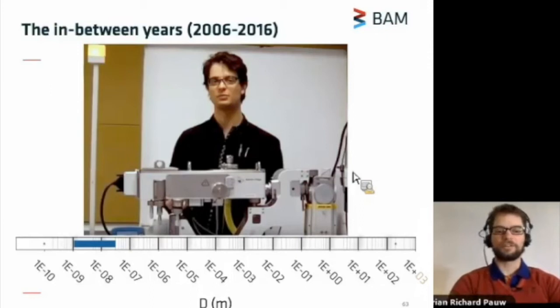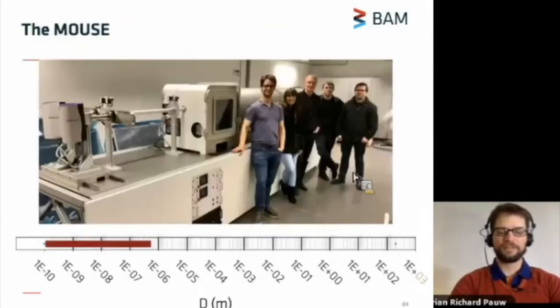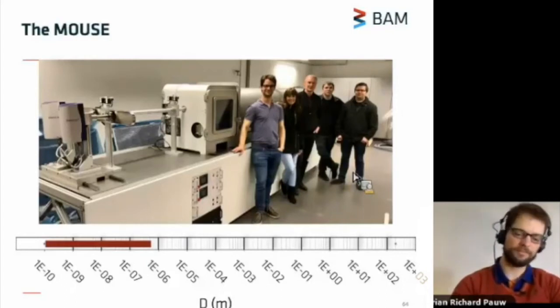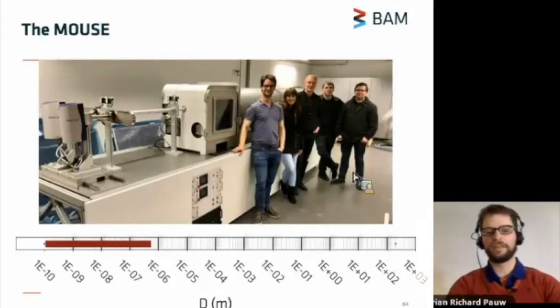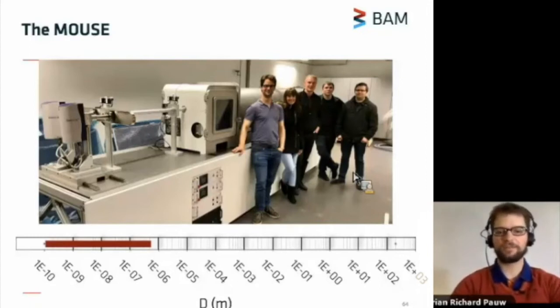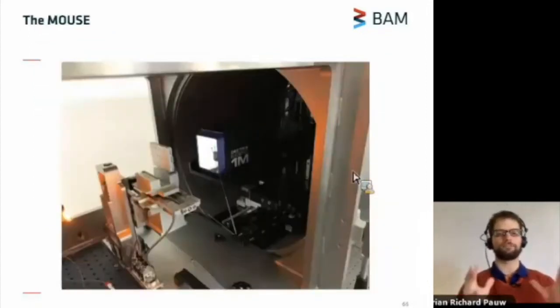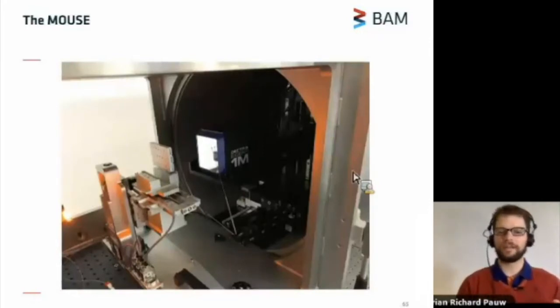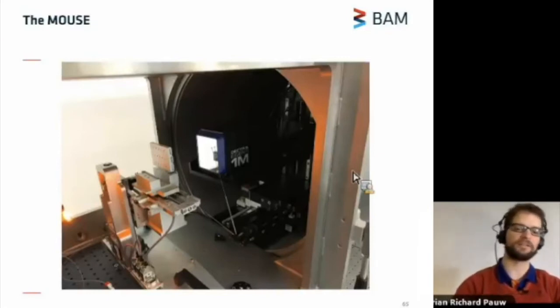And then our instrument came, and you can see that this instrument measures over a very wide angular range. And we do this for every sample. The reason we now measure over this range for every sample is because it's easy. We have a detector which sits in vacuum on a motorized stage, so we only have to program the machine to measure in a particular configuration. So for every sample, we measure at least three or four different scattering patterns.